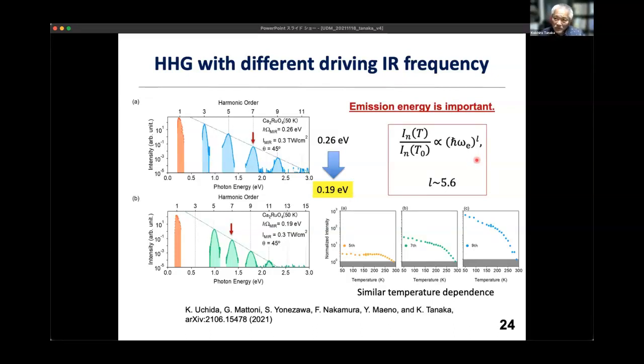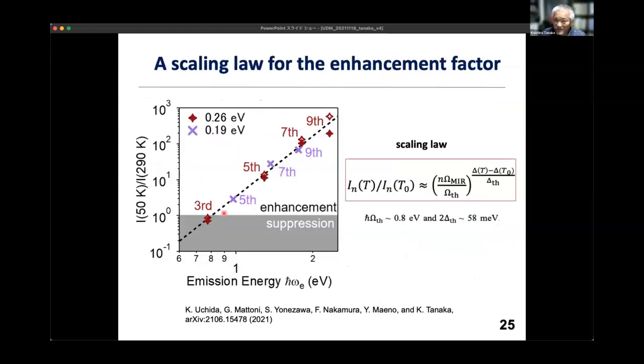So we plotted these two-color excitation results in the same figure. I showed the result of using 4.8 micron, and then we also did 6.5 micron, and taking each data set we obtained this enhancement factor. This is a ratio between two temperatures, the intensity ratio. This is the enhancement factor. And as you can see, if you plot this enhancement factor as a function of emission energy, we can see a very nice straight line in log scale.